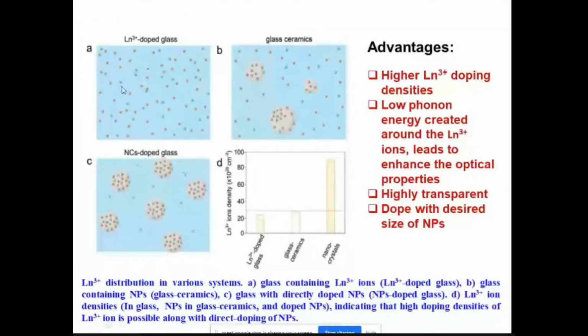Now just to see, this is a normal glass where these are the active rare earth ions. And now the glass may become a glass ceramic. Just to see, the round bubbles are nothing but glass ceramics. And now you are doping the rare earth activator ions. Nowadays the activator ions are available in nano size also. And now I can dope the nano lanthanide so that a glass becomes a nano glass. So this is a normal glass, this is the glass converted to glass ceramic, and this is the glass where the nano crystals are doped.